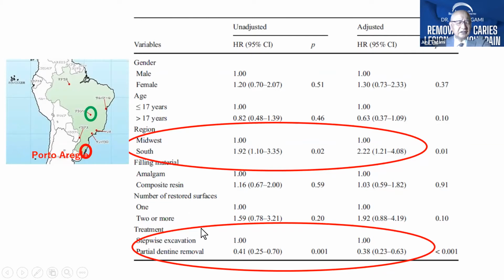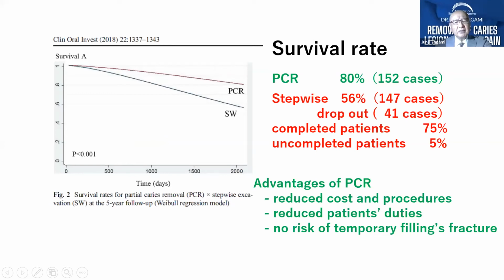And also another important piece of information is that the treatment methods, stepwise excavation and partial removal of caries, were very different from each other. The stepwise excavation showed more failure cases than partial removal of caries. As a result, the partial caries removal technique showed an 80% success rate, survival rate after 5 years, and the stepwise technique showed a 56% success rate.